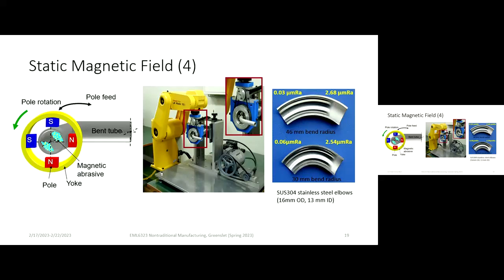So here we have actual results of 2 different bent tubes. The second one on the bottom is a much tighter bend radius than the one on the top, but we're able to get, as you can see, very, very shiny surfaces. You can see those edge regions were left unfinished just for comparison. So this is before MAF, after MAF, before, after. And we have roughness values to show you exactly and quantitatively how much of a difference it made. So we went from 2.68 microns Ra to 0.03. So that's a significant difference. What is that, like 1% roughly of what it was originally? And then on the tighter bend radius, not as good as the larger bend radius, but still very, very close. So we had 0.06 microns Ra from what was originally a 2.54 Ra.